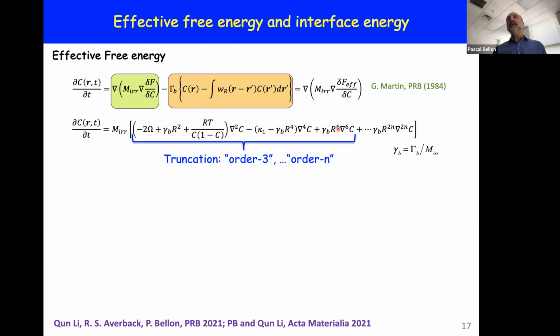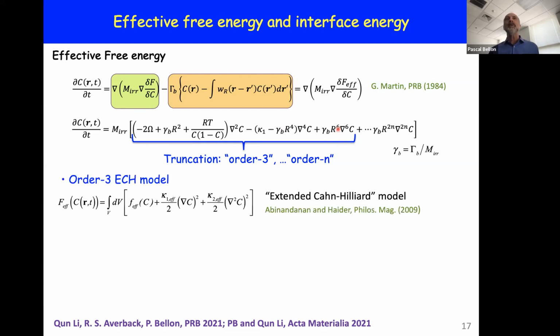And we show that it's sufficient, to some extent, there's a lot of useful things to learn just simply by truncating that expansion to the third term. So we refer to this as an order 3 model. And then we showed that essentially the effective free energy that you end up obtaining is one where there is an effective free energy density for the homogeneous state.